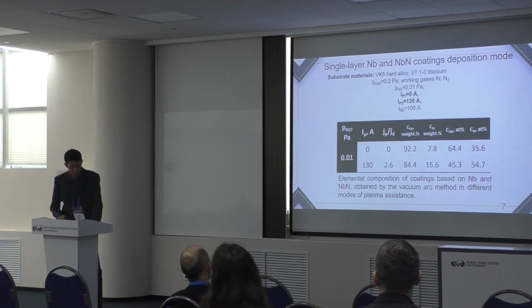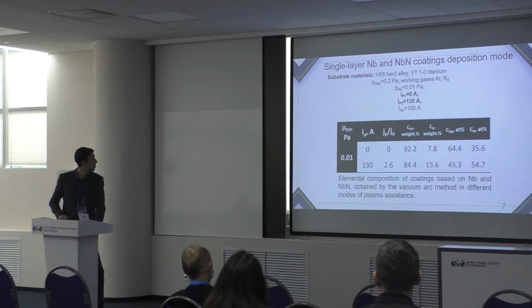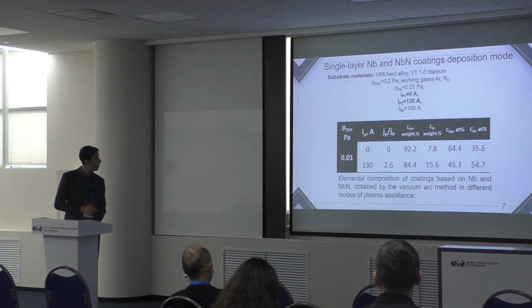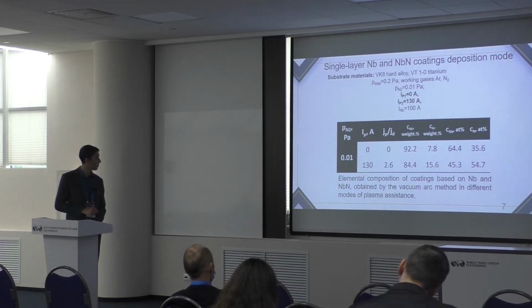To identify the necessary modes of obtaining multilayer coatings, we first synthesized and investigated single layer coatings. Their thickness was about 3 micrometers. The metal coatings were applied without plasma assistance, and the nitride coatings were applied with plasma assistance, and the current of the non-self-sustaining arc discharge was 130 amperes. As you can see, the concentration of nitrogen in our coatings is higher than in the coatings without plasma assistance.